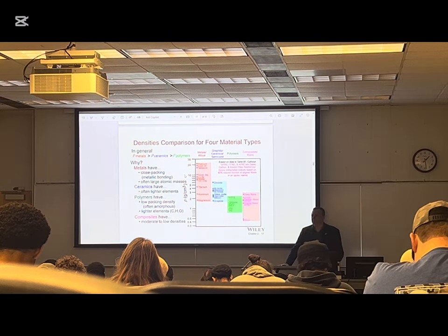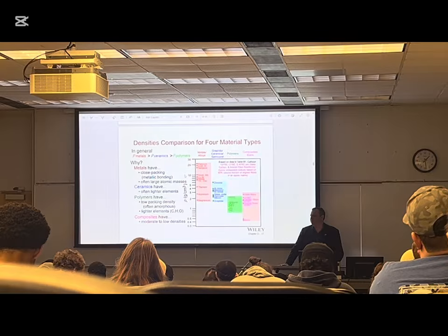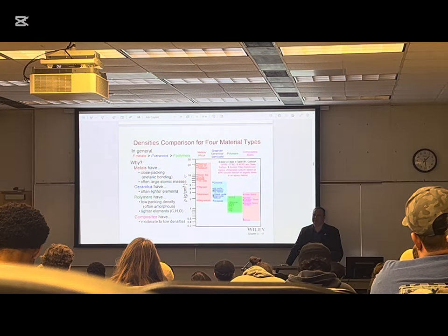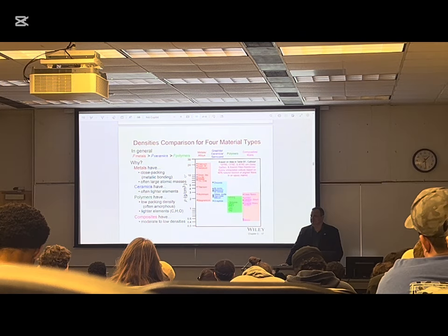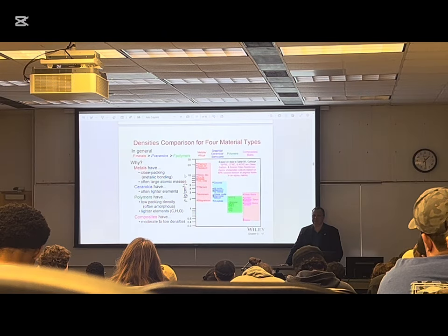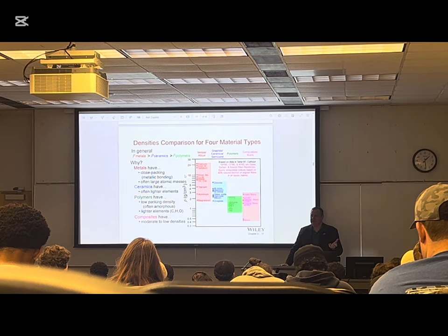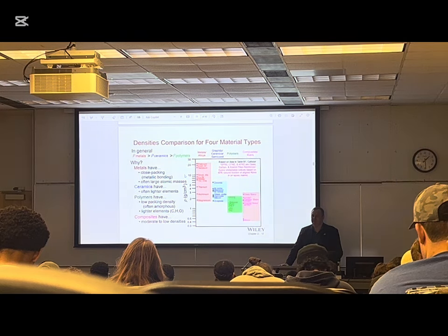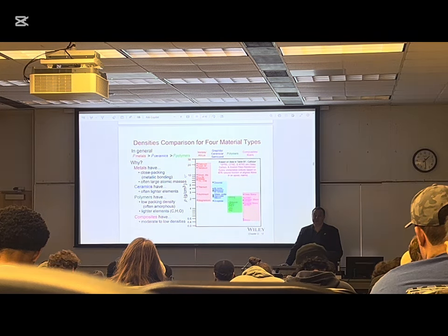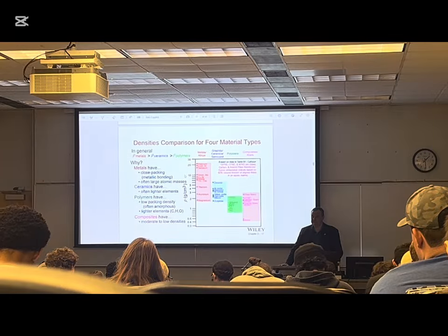So, do you think it's cool or not? We've taken some really advanced chemistry and physics that we covered in the last lecture and said, okay, let's use spheres, and spheres represent atoms. And we just calculated that the best packing is 74%, meaning that there's 26% free space.